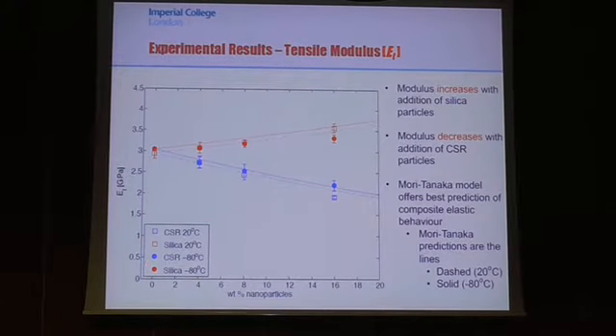I must point out as well that we did all these tests at about 20 degrees, so nominally room temperature, so 20 plus or minus a couple of degrees, and also at minus 80 in a liquid nitrogen chamber. So the Mori-Tanaka model I've included as well for both the predictions, and they offer a reasonably good prediction of what the actual composite modulus is. The dashed lines are the results at 20 degrees, and the solid lines are the results at minus 80. So one of the things we can see here is that the modulus actually doesn't change all that much between room temperature and minus 80 degrees.